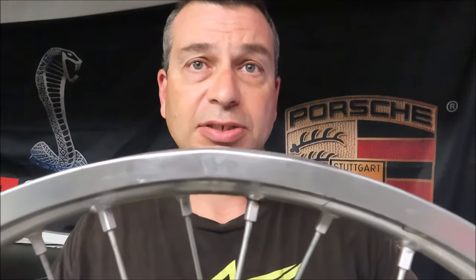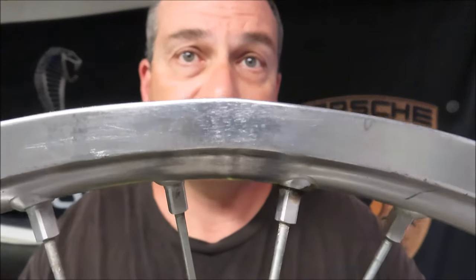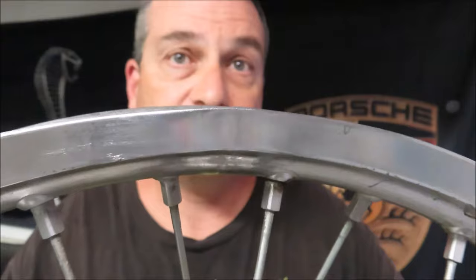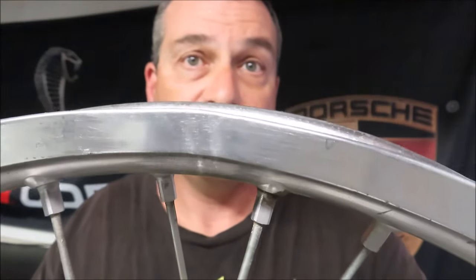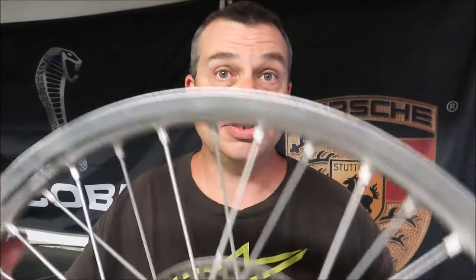I'm still not completely sure what went wrong. I heated the wheel up to about 100 degrees hotter than I heated up my test piece of aluminum, and those aluminum welding rods would just not melt at all. In fact, as you can see, the crack is gone. There's no crack on either side anymore. I went ahead and cleaned it up a little bit. But as you saw earlier, the rim started to kind of press together, I believe because it's under tension from the spokes. As I was heating it up, I think it was just kind of squeezing together. So it created that little band around the rim.